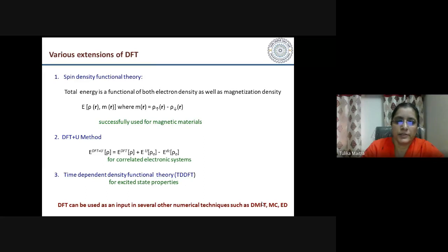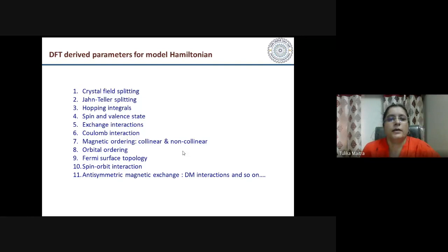Okay, so this is the basic introduction of DFT that I wanted to give you, and then what all we can derive, what are the parameters that we can derive for constructing a model Hamiltonian from this DFT calculation. So when we do electronic structure calculations, we can calculate the crystal field splitting, Jahn-Teller splitting, hopping integrals. So I will discuss some of them in the next few slides. Spin and valence state of the various ions, then magnetic exchange interactions, which are very important for magnetic materials. Then Coulomb interaction, as I said, that we can calculate from the constrained DFT calculations. And you can also determine the ground state magnetic ordering for collinear magnetic ordered state, or non-collinear magnetically ordered state. Then another thing that you can calculate is orbital ordering.